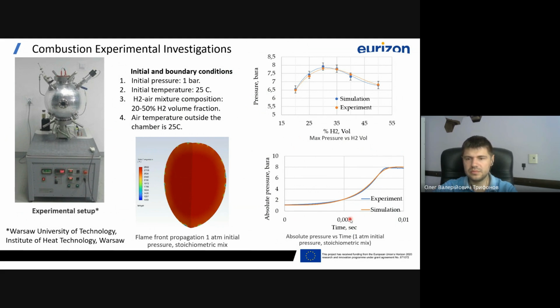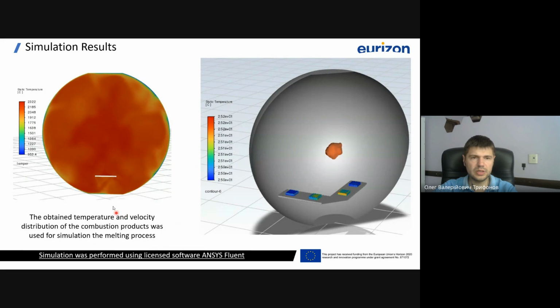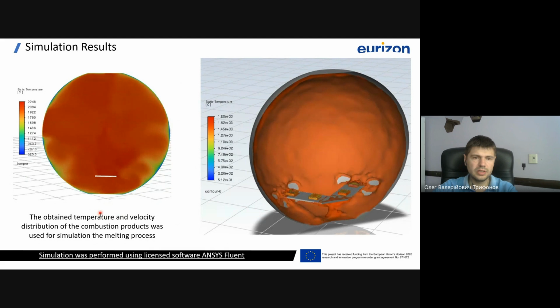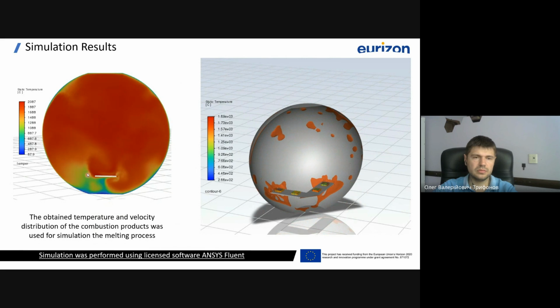Some validation results we can see on the screen, and this experimental investigation was carried out with support of our partners from Warsaw University of Technology. Our colleagues provided us experimental equipment and helped us to carry out the experiments, and those results were very useful for development of a correct simulation model. So as a result, we obtain the initial temperature distribution, and initially we use the temperature exactly after complete combustion, the moment when all the fuel mixture was combusted.